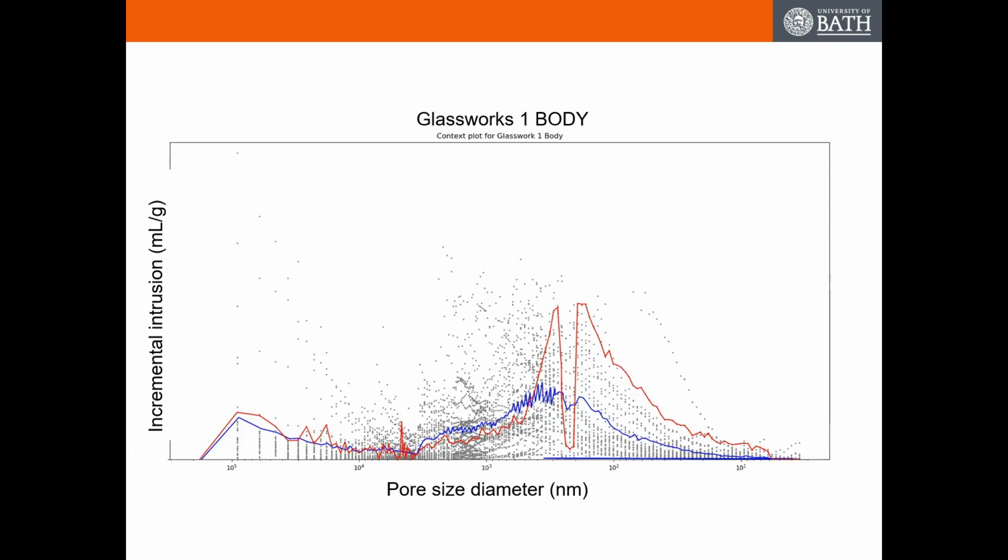And the material was like a powder. When I say I took a sample, I could pull it off with my fingers. So at this point, I was thinking freeze thaw. Yeah, seems reasonable. Blocked gutter, everything's saturated. Something happening inside it that's caused it to break down, open up a lot of fine pores and micro cracking.